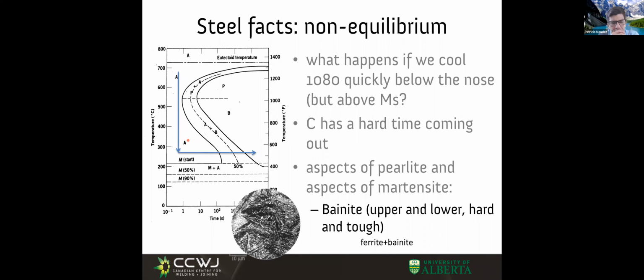And now that I've taught you that, I can show a start of transformation and an end of transformation that ends up in pearlite—coarse pearlite on top, fine pearlite at the bottom. And then if we go crazy and quench to room temperature too fast, we get martensite.